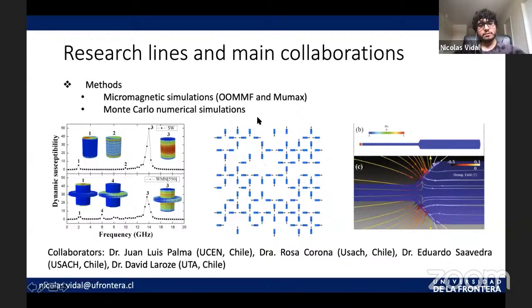Related to the Monte Carlo simulations, here we have a lattice, an artificial spin ice, in this case with vacancies, with the idea of computing the energy, which is the best scenario in relation to the percent of vacancies in the system.